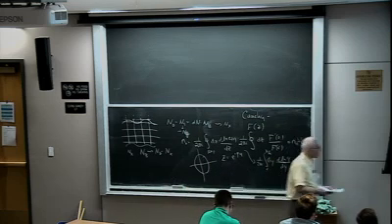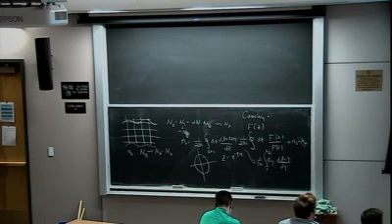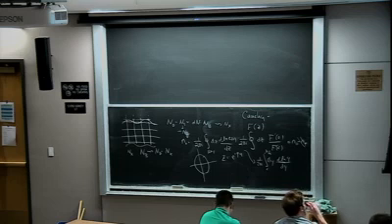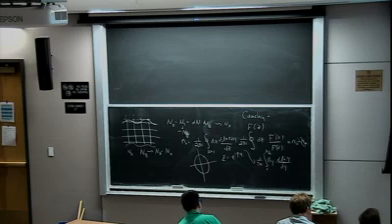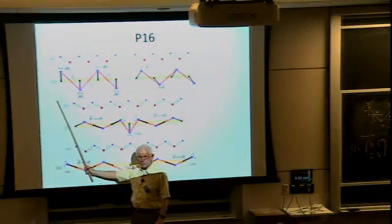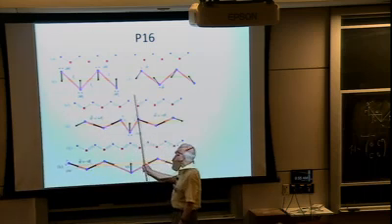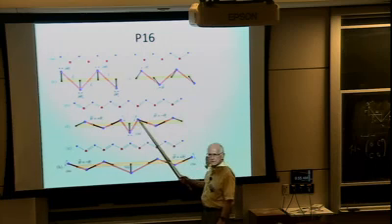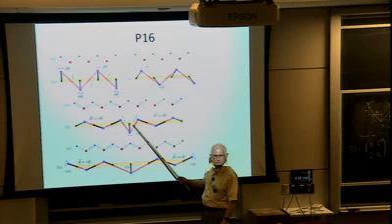Now, it turns out that this also implies that if we mix the two together and get a domain wall that separates a theta positive from a theta negative, then if I look at this, we have something going to the left. If I cut this right here, there's a 0 mode going in this direction, and we know what that 0 mode looks like. If we cut it this way, we've got a 0 mode going in the opposite direction, and we have an amplitude for each of those. Now I need to connect these two together to create my domain wall.